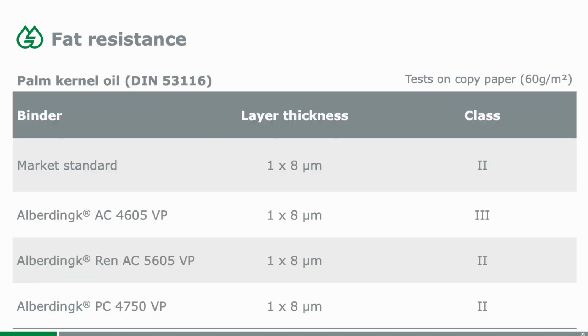So how do the products actually compare? Here we use the copy paper as a substrate and a slightly thicker film thickness, so 8 microns in this case. And you can see that only the 4605 is slightly weaker with class 3, but all other products are actually in class 2.